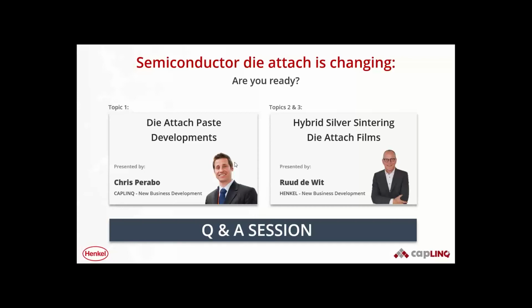We looked in the past at sintering films, but the difficulty is that they become pretty brittle to handle by the high silver loading. They also needed some pressure for a second or some seconds to attach. Nevertheless, this may be something we are going to look into again, but that's still to be confirmed. But if I talk about conductive films, basically these are B-stage layers of silver in a resin. When you do the die attach, you need a low force and 120, 130 degrees. Then you attach the joint, and then it goes into an oven and gets its standard oven cure. So no pressure during the cure.